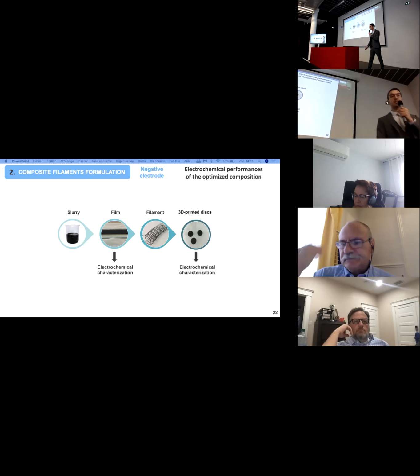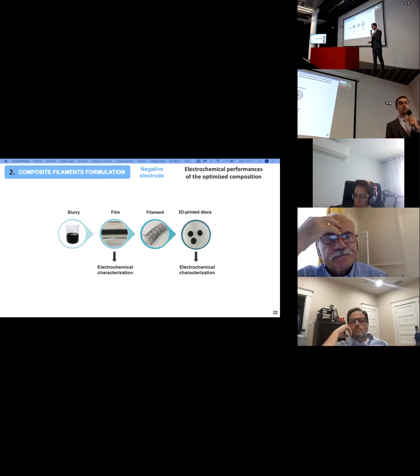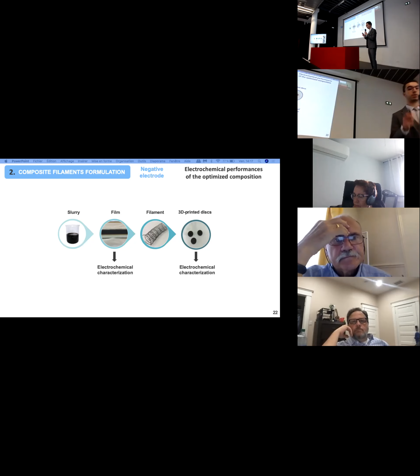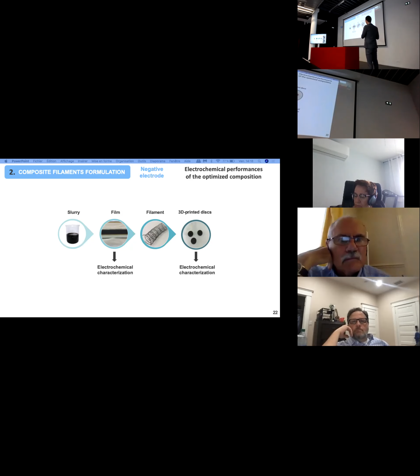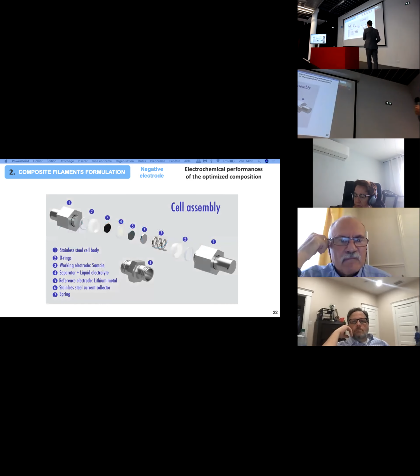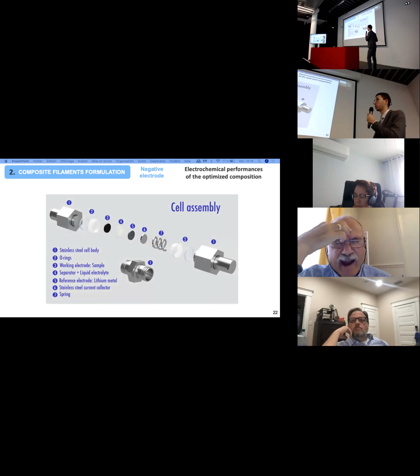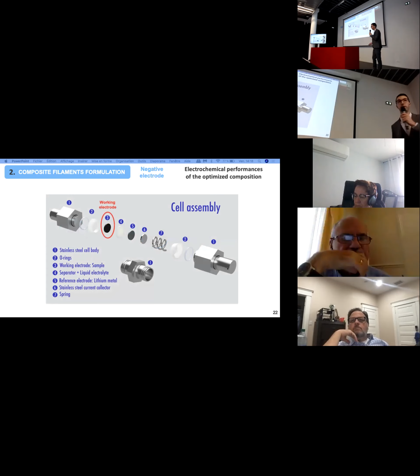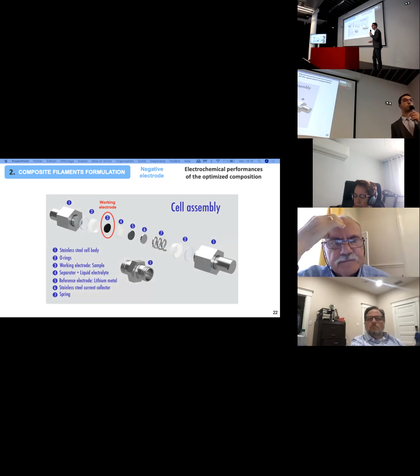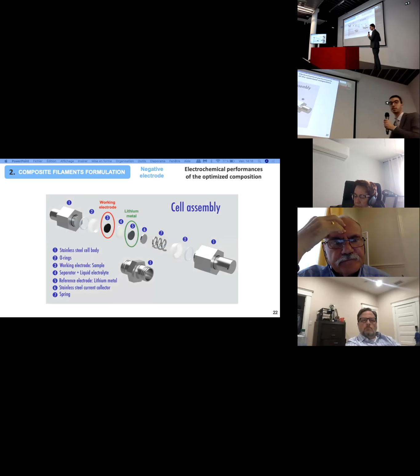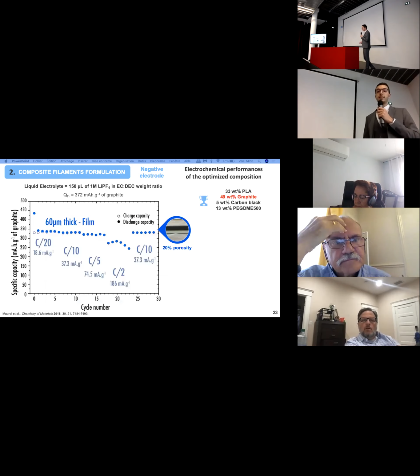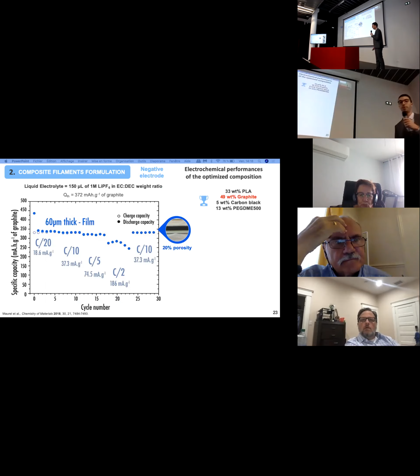Okay, perfect. So we did electrochemical characterization on both films and 3D printed discs. Here we also cut some discs from the film, and we inserted those discs into a classical swagelok cell. Here we got our working electrode, and we tested that versus lithium metal. This is really classical. From this, we were able to check the electrochemical performances.